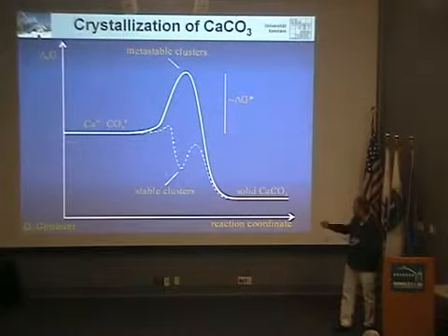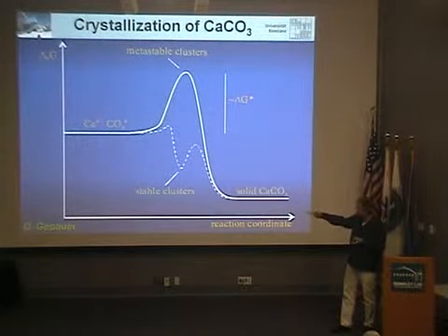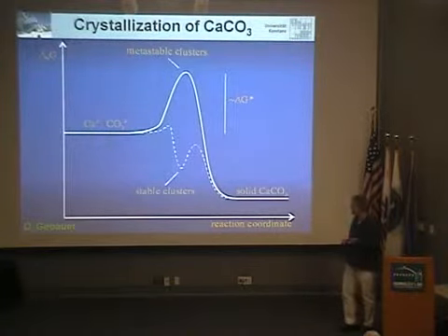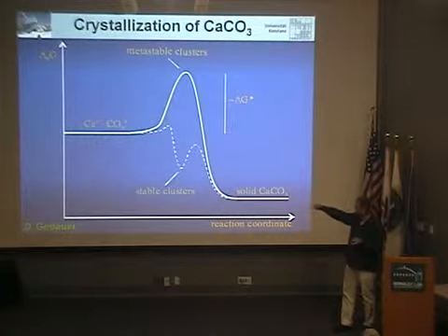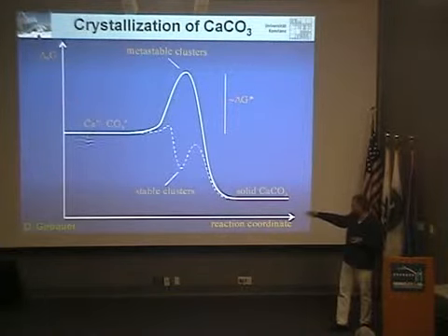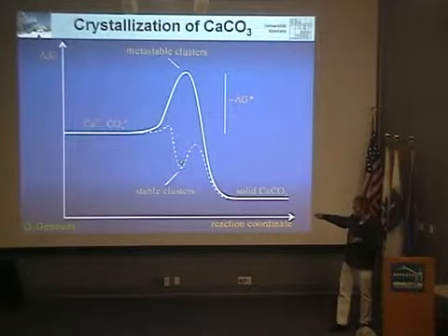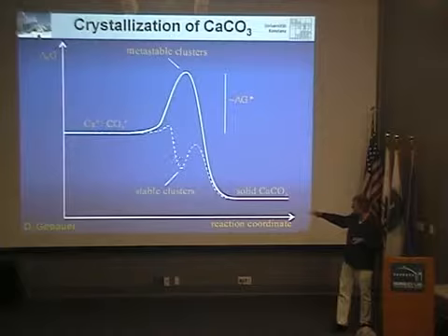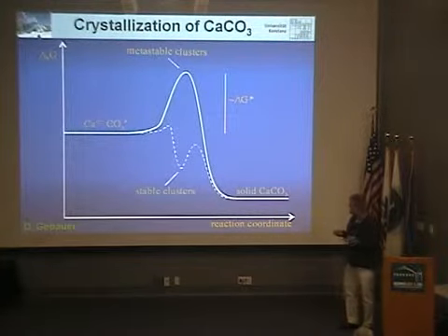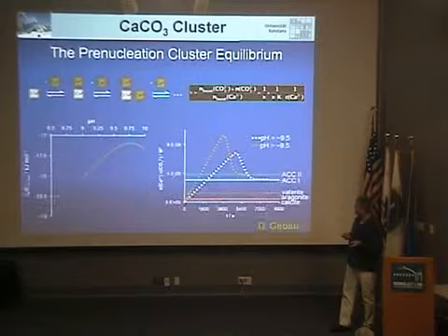And if you plot it in an energy diagram, you can see it like this, that we start with ions, and finally, we have solid calcium carbonate, in our case, amorphous calcium carbonate. So the classical way would be that I form metastable clusters. They fall either apart or they can grow. And the alternative pathway, which we have now, is that we got a minimum before we form amorphous calcium carbonate, which is stable towards the ions in solution, and via activation energy, it forms amorphous calcium carbonate by passing this activation energy barrier. So that's the pathway.